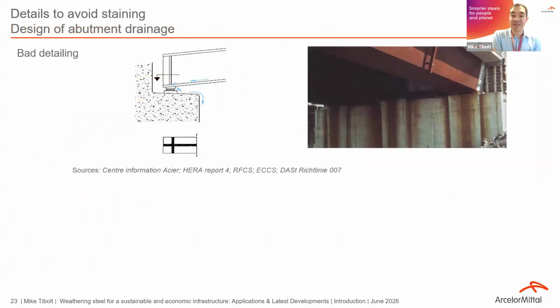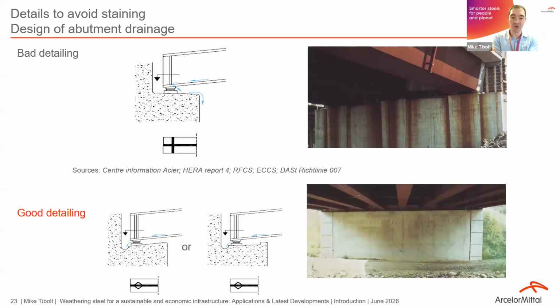Then also, to avoid the staining of, for instance, the abutments, you should have a drainage which avoids that the water can accumulate these rust particles and then get into contact with the concrete surfaces of the abutments. So the bad detailing would be like shown above. On the bottom, you see how you should do it. You should incline the wall of the abutment on the back of the bridge, so that the water can drip off, and apply a drainage system at the back of the abutment walls, so that the water can be evacuated without getting into contact.